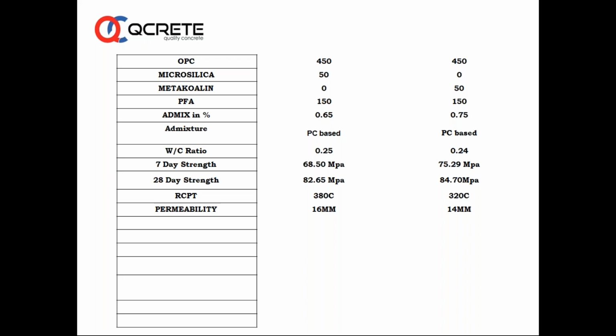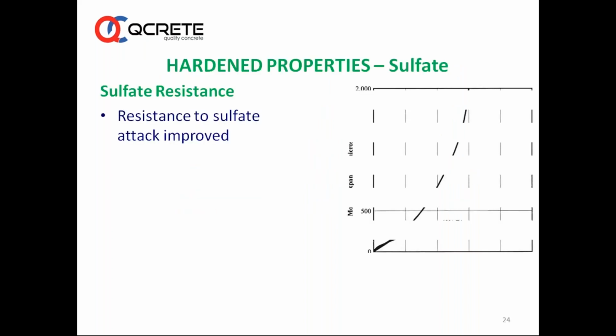So as I said, it is not necessary that we have to stick to only OPC or fly ash or something like that. Depending upon what strength you want, what performance you want, you can change the SCMs. By using microsilica and metakaolin, we have reached RCPT values below 500. Permeability as measured by DIN 1048 is lesser than 20 mm, something like 14 mm, 16 mm and so on, which indicates the concrete is pushed to a very high level of durability. So RCPT values below 500, as depicted here, can be easily achieved by using SCMs, and it is very difficult, I'm not telling it is impossible, to achieve with only OPC. Next one.